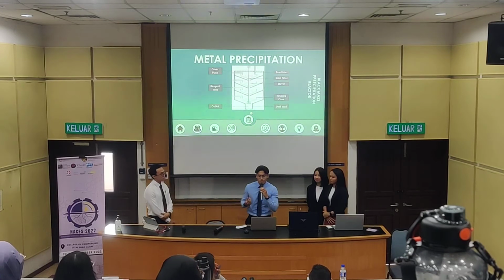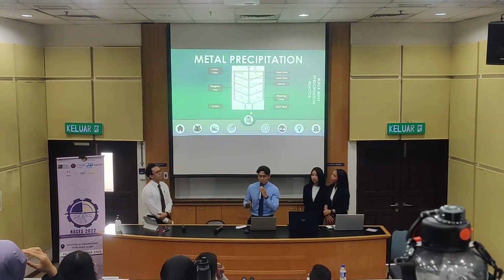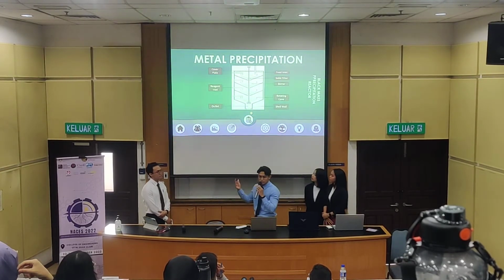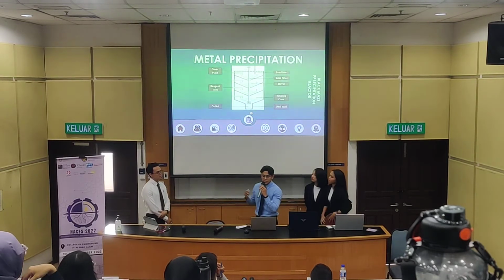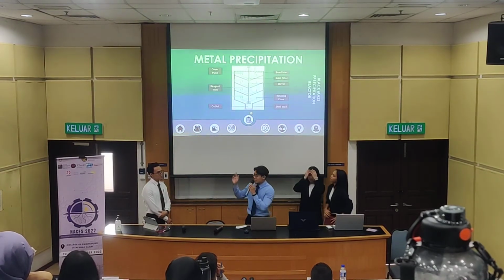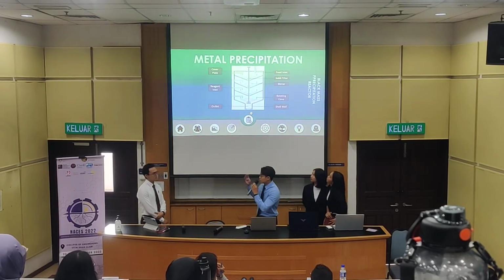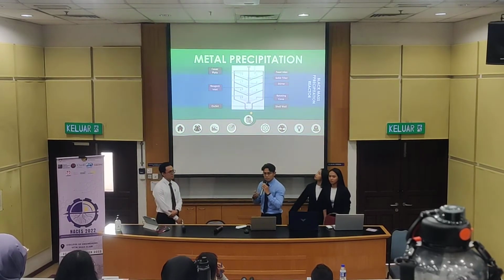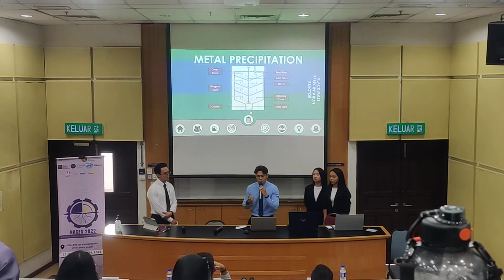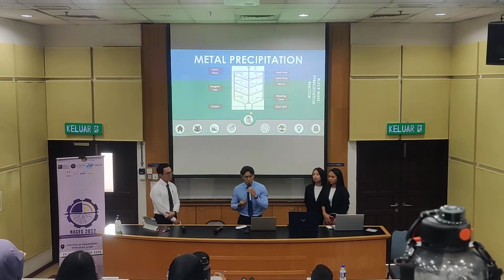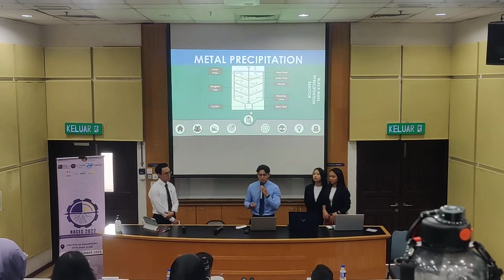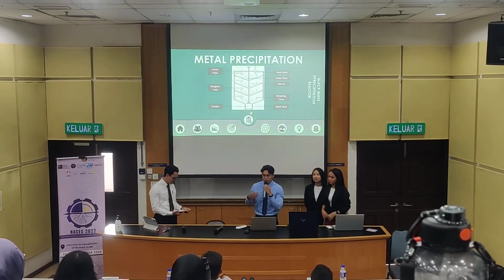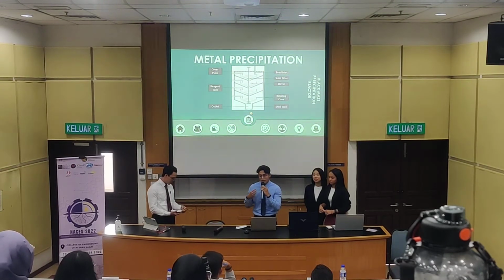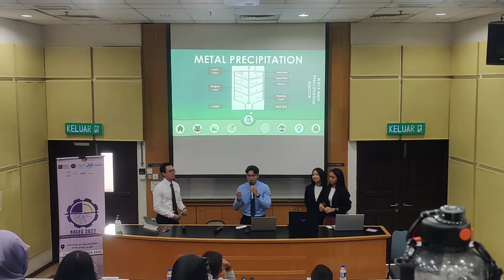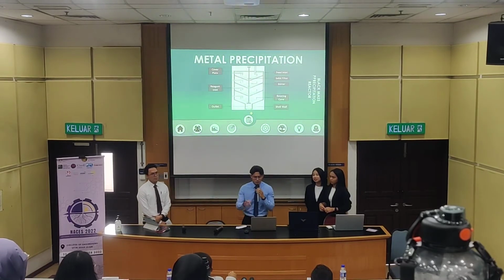So next, we proceed with our main process, which is the metal precipitation process in our proposed reactor, which is a metal precipitation reactor. So this is the side view of the reactor interior, showing 4 stages of precipitation process. The reason why we propose this type of reactor is because a reaction in citric acid media favors a combination of selective precipitation and solvent extraction, which can effectively recover and separate each metal from the leached solution.